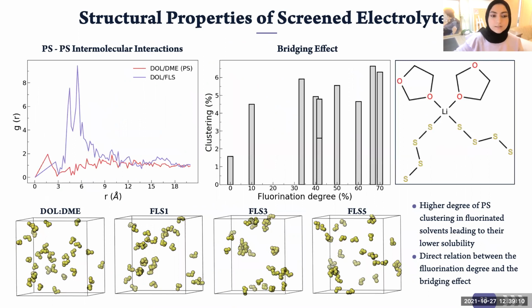Here I'm showing the radial distribution function between the polysulfide species in the solution, and it is evident that in the fluorinated solvents, there is much stronger interaction, indicative of the formation of a clustering effect of these polysulfide species in the solution, and therefore lower solubility. And it's also evident from the snapshots here, where if we compare DME to FLS3, the region is more heterogeneous. In the FLS3 solution, we can see much bigger clusters than that in the conventional electrolyte.